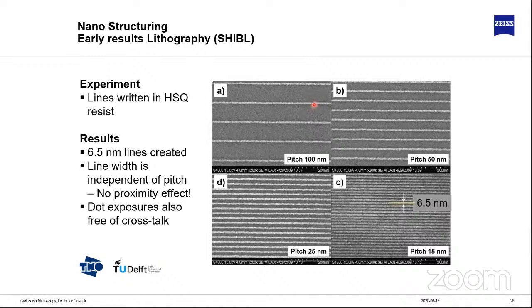That means for an electron beam, what you would observe is if you have a single line, you have a very thin line. If you have a dense pattern, your line width changes, it becomes thicker due to the fact that we're generating backscattered electrons, and they will do some exposure around the area where the beam hit the sample. For ions, we do not generate any backscattered electrons. That means we do not get any exposure outside of the area where the beam has hit the sample. And that means no matter if we do single lines or a dense pattern, the line width does not change. So currently the best that we could achieve is something like 6.5 nanometers.